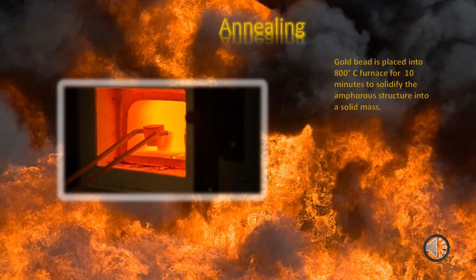It is accomplished by placing the bead into a scorifying dish or small crucible and heating it to roughly 800 degrees centigrade for about 10 minutes. Structurally, the bead will slightly melt internally, filling in those small, minute pore spaces, resulting in a solid structure, after which all of your beads can be melted and poured into a single wafer or bar of purified metal.